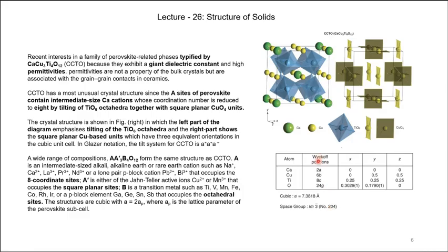And this is the Wyckoff position. Calcium belongs to the 2a Wyckoff position, copper 6b, titanium 8c, and oxygen 24g Wyckoff position.